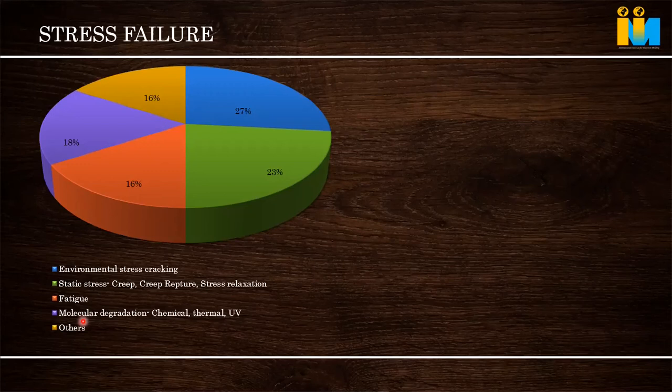If we are using polycarbonate in a petroleum atmosphere, it cracks within 5 minutes. In an acetone atmosphere, it cracks within seconds. So we have to select the material properly. Crack means the molecule is getting damaged. There we have to use PE, PP only, or nylons. That is a chemical molecular degradation, and it could also be due to excessive temperature.